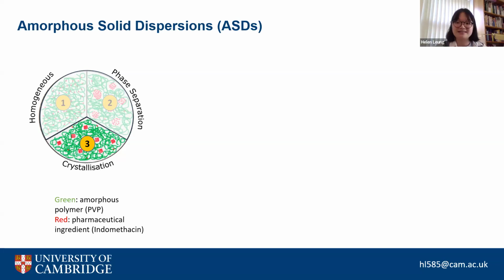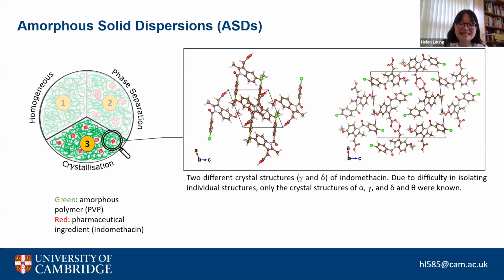But over time, because this is metastable, you can get phase separation of this polymer and your drug. Eventually you can get unwanted crystallization, which can affect the shelf life of the drug and also potentially the performance of that drug. So we were interested to see what the crystallization in an amorphous solid dispersion looks like, and can we see that with electron diffraction? Can we understand potentially the origins of the crystallinity and the whereabouts? The crystallinity can take many forms. So in indomethacin, this drug, there have been a handful of great 3D ED studies on this as well.